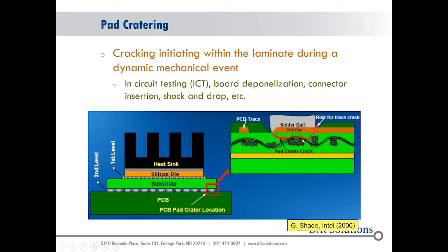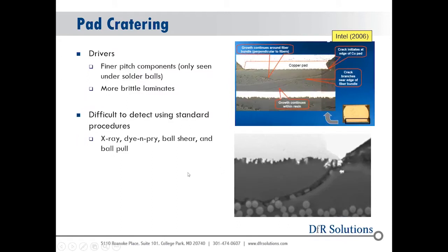So what you're doing is letting escapes into the field where there's not much holding that solder joint onto the board except for a very small portion of copper, which could break under a little bit more mechanical load. Just some more pictures of it. We also saw a little bit of an uptick in pad cratering when we went to lead-free because of the stiffer solder, and a lot of the laminates, we had to go with higher glass transition temperature laminates. They tended to be a little bit more brittle than the typical laminates we were using before.